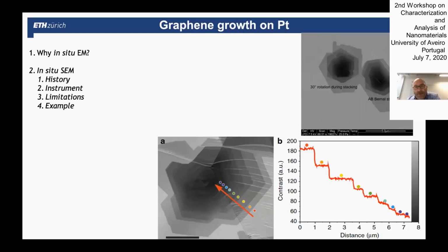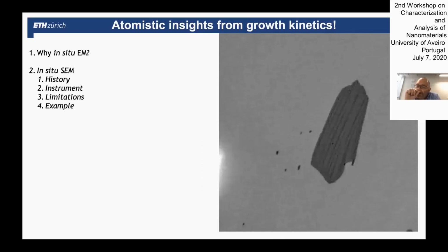SEM doesn't look like an atomically sensitive tool, but in terms of the lateral stacking on graphene, it is really atomically sensitive. And then I would like to show this example to show you that you don't always need a TEM to study things that are related to atomistic processes. We have here graphene islands, a big one and a few small nuclei. And I will run the video and you will see how these individual islands all coalesce together to form a single or a polycrystalline film. And I just do that now.